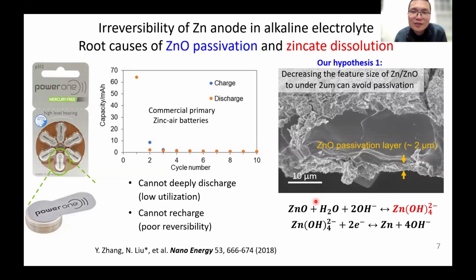The second root cause of the problem of the zinc anode is zincate dissolution. During the conversion between zinc oxide and zinc, the zinc species will go through a zincate ion, as shown in red color. This zincate ion is soluble. It doesn't have a lot of solubility, but it's enough for the species to move around, and the shape of the electrode will change over cycling. Even though you start with a nice shape in the beginning, it will aggregate and grow at places you don't want after cycling. That is the second root cause of the zinc electrode problem.